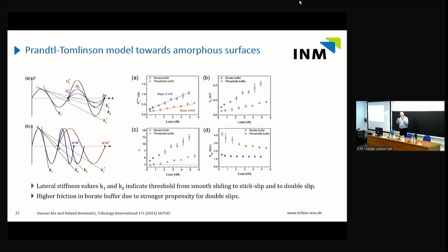And then you get an instability, essentially, when your force is high enough to overcome the maximum force, you will jump to the next minimum, and you will jump along the path of your stiffness, essentially. And then he has simply changed the potential. I say, well, amorphous surface means either that the potential is locally higher or lower, which is the upper panel with the blue and the red curve, or that actually the distance to the next minimum is larger or smaller than for a periodic surface, which is the lower panel, red and blue curves.